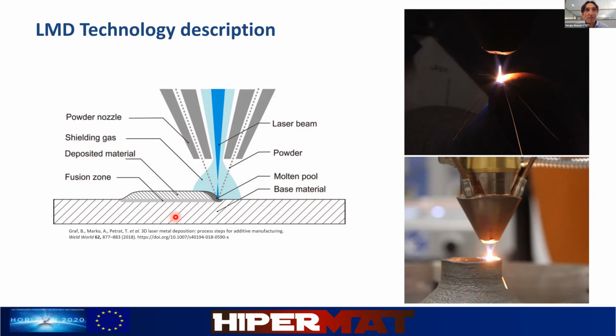If the base plate, or base material, is fixed and the nozzle, that is this part, is moving, we leave a track of deposited material. And if we look closely, we can see that the base material is melted below the deposited material that is on top. In this case, it is called the fusion zone. This is melted material in the base material. So this means that the powder material will be mixed with some quantity of the base material, and this will affect the properties.